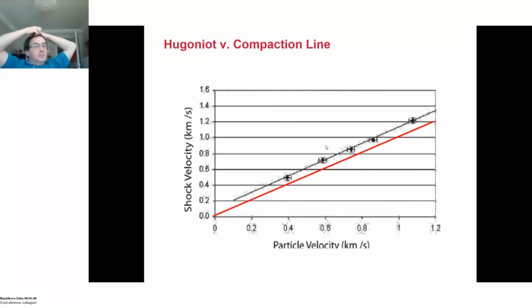And there is a small offset, and I would argue that there is a small amount of heating occurring in the system. And yes, there is a small amount of energy therefore being placed into that compaction wave, and that's causing a mild increase in stress in the system compared to pure isothermal compaction. But again, the differences we're talking about here are fairly small in the grand scheme of things.